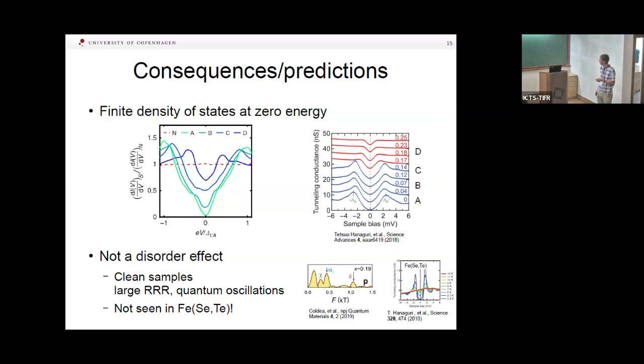And as you can see, in the pure case, there is no density of states at zero energy, whereas it's not so easy to see because of this offset, but it turns out that starting from 17% doping, the density of states at zero suddenly jumps to a finite value, which is reminiscent of a two-dimensional Bogolubov Fermi surface appearing in the superconducting state.